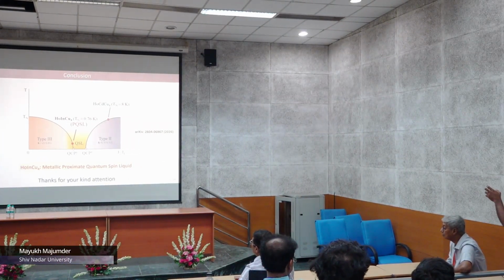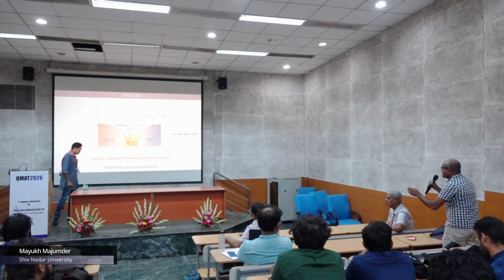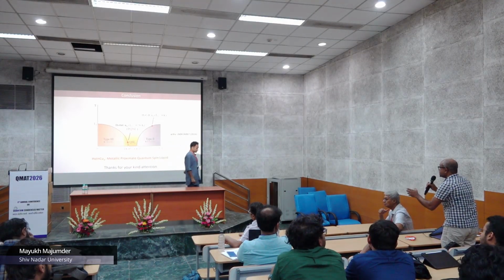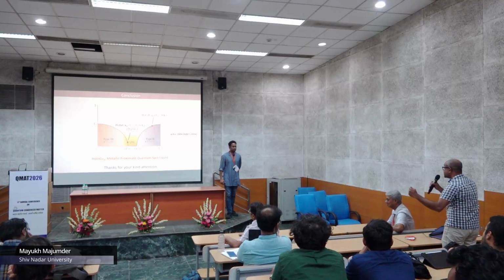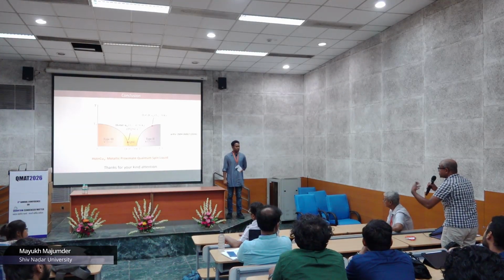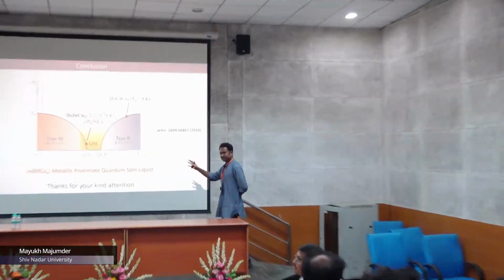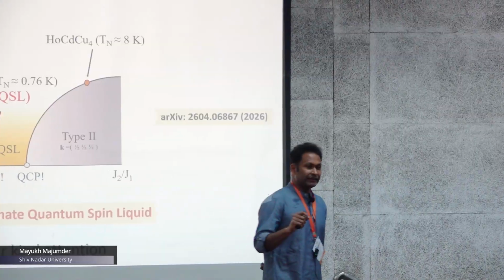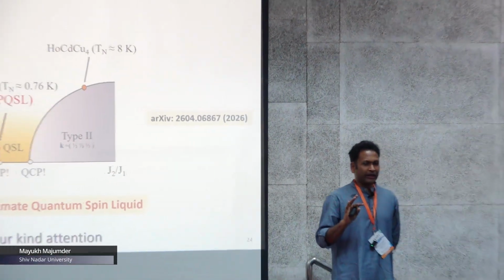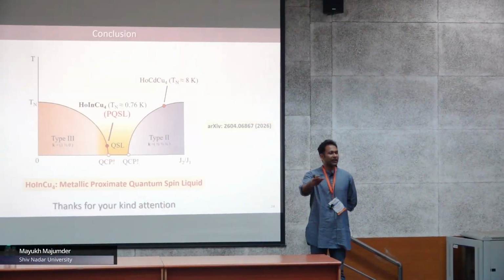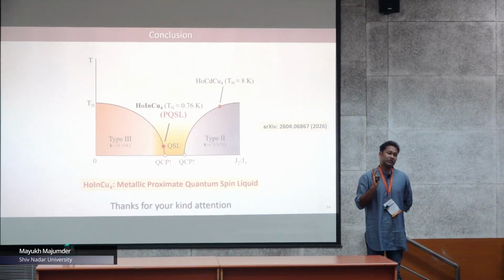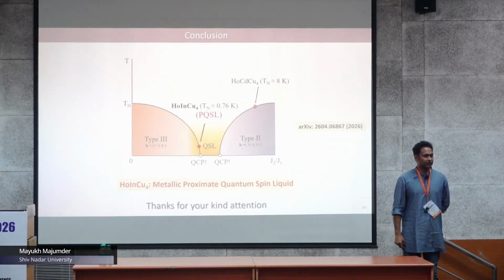Okay, so what provoked me is that if we can really tune the system, because you are targeting this metallic proximate quantum spin liquid state, it's always good to tune the system in one direction. So it's good to have a single crystal for this system. As I told, the sample has been synthesized by our collaborators, and they have single crystals. So in principle, if we really think about uniaxial pressure or something like that, that can be done in the future.